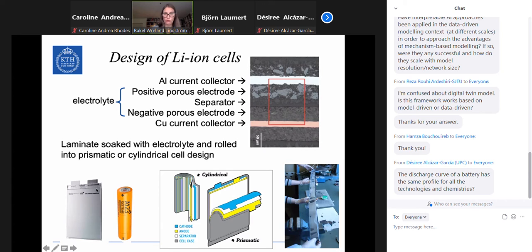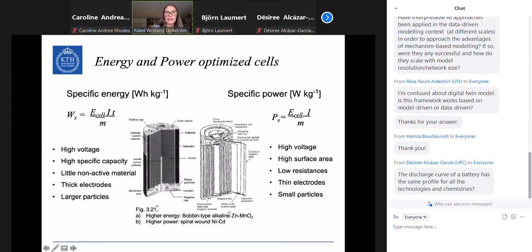But if you don't have it in a roll, then you have to press the cells together so that you have good contact through all. Depending on the design of the battery, you can either have it energy optimized or power optimized. For high energy, you should have as much active material as possible and as little inactive material as possible, and you make thick electrodes, large particles. For high power, you make thin layers with small particles. You have large surface areas, so you can reach high currents in a short time. This means that you have lots of inactive material, and then we have a lower energy in this type.